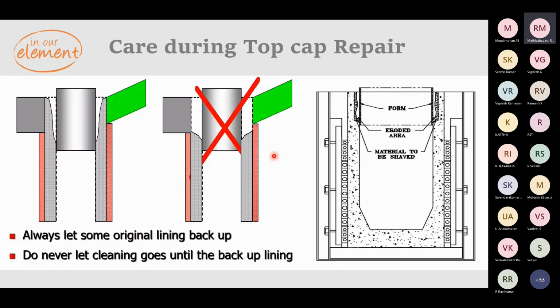When it comes to care during top cap repair, whenever you try to repair, don't remove the complete lining on the top. Always try to keep the original lining as a backup, as shown in the first picture. So don't do like this. Don't remove the complete refractory. Partially remove the hot face and then set a form and then fill it either with a dry version or a castable version or go with the plastics. But always let us have the original lining as a backup.